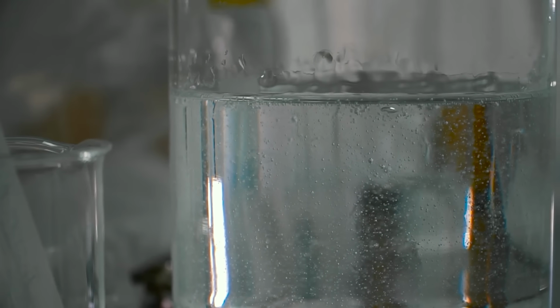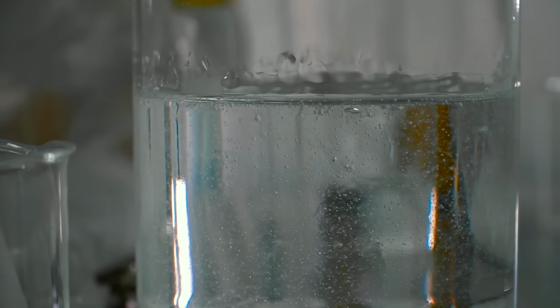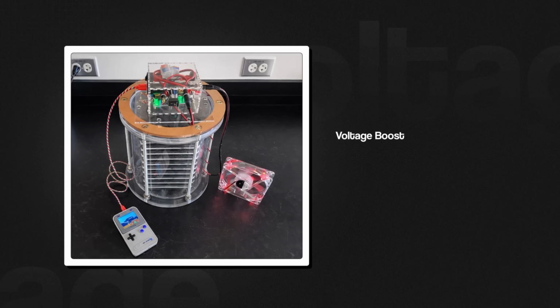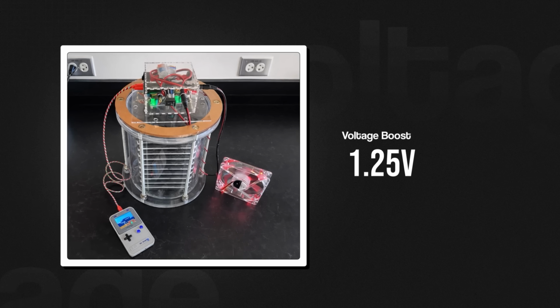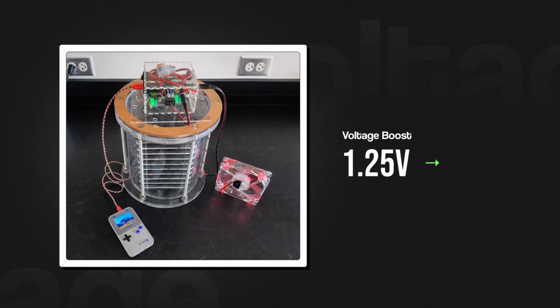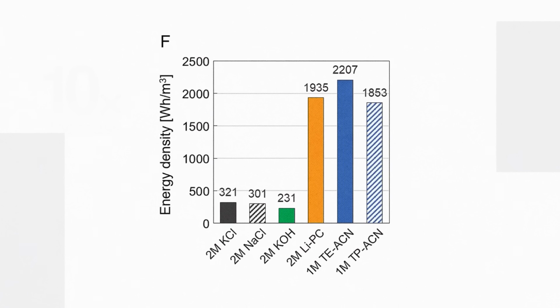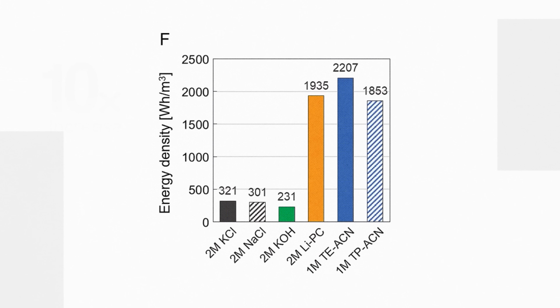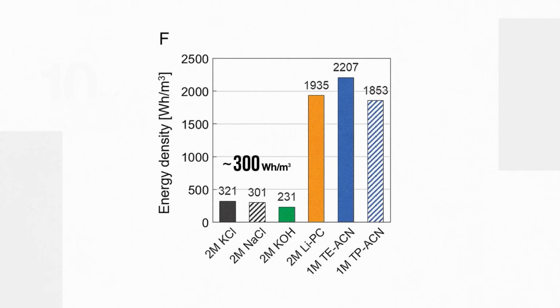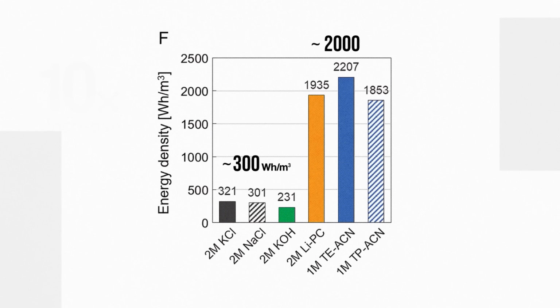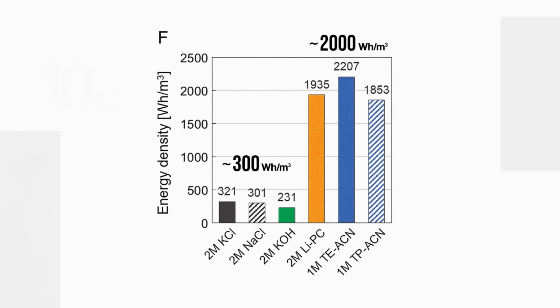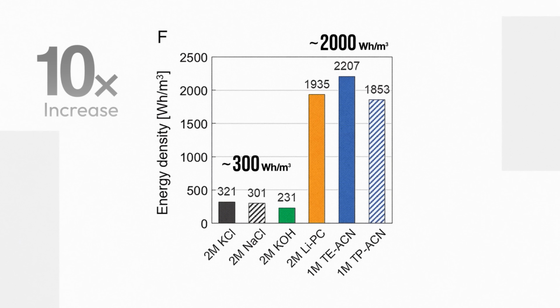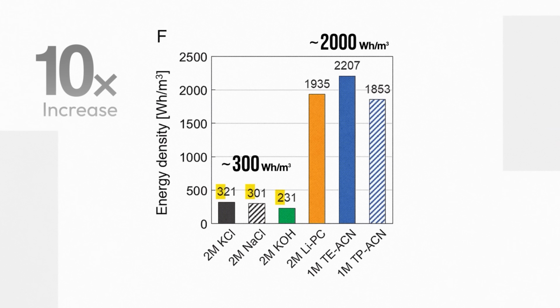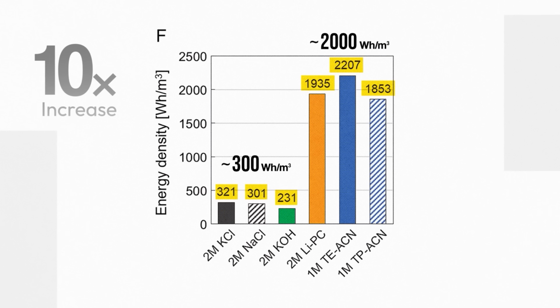The organic electrolyte is more expensive and harder to work with, but it boosts the voltage of the supercapacitor from around 1.25 volts to up to 3 volts. This takes the system from an energy density of around 300 watt-hours per meter cubed to around 2000 watt-hours per meter cubed, with the tenfold increase referring to the jump from the worst to the best performing combinations.